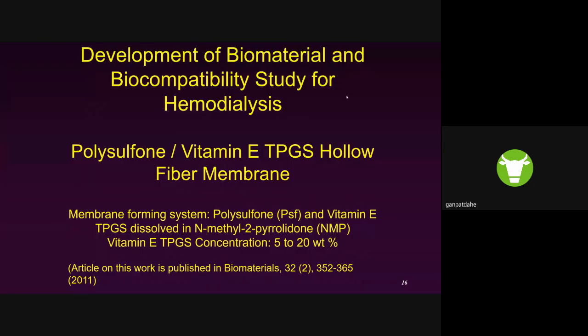And now I'm going to talk about making the biocompatible hollow fiber membrane. Here, what we did is use polysulfone and vitamin E TPGS polymer to make this membrane. The membrane forming system consists of polysulfone and vitamin E TPGS, and both these materials are dissolved in N-methyl pyrrolidone, which is a very good solvent. NMP is a very good solvent for polysulfone. And here the concentration of vitamin E varied from 5 to 20%.